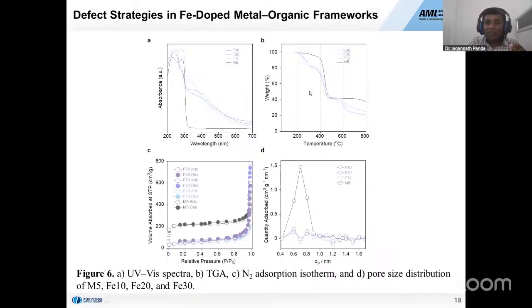And structural stability. In the case of M5, this is highly stable. But whenever iron is introduced, the stability decreases, but not by that much. It is still stable up to 600 degrees Celsius.